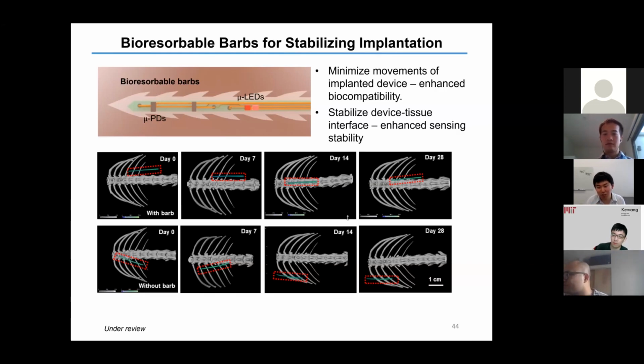That's the advantage of using two photodetectors, which can cut off the baseline shifts to a large extent. But still, the environments of the two photodetectors may experience slight variations, and that variation may contribute to the baseline shift. If we use these probes for a long period, a few days, we may see a slight shift of the baseline, and it requires calibration mechanisms. That's also a limitation applied to even some commercially available optical sensors. They require calibration steps after long-term studies. So that's the strategy we are using here. Yeah. Thank you. Great point.